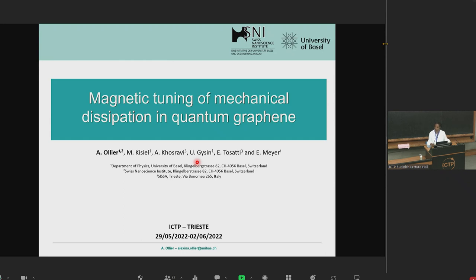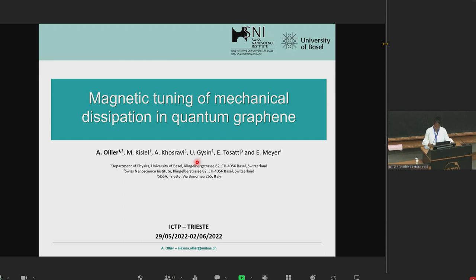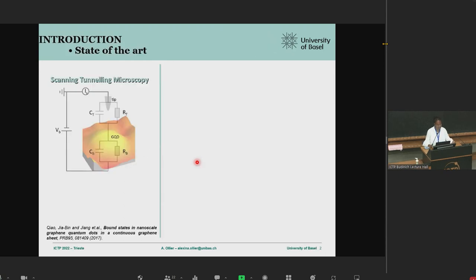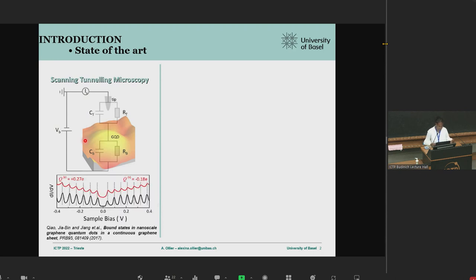These quantum dots can be defects or surface deformations, and we are using a scanning probe. With scanning tunneling microscopy (STM), it has been shown that surface deformations — like a puddle — can behave as quantum dots. We can charge and discharge this surface deformation. In the dI/dV spectroscopy, here you have the density of states, here you have the energy, and every peak you see is a charging event occurring in this quantum dot.